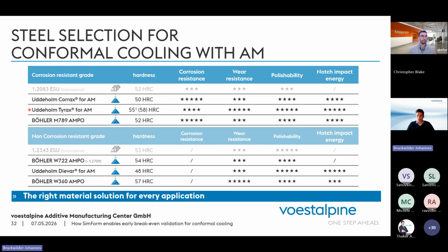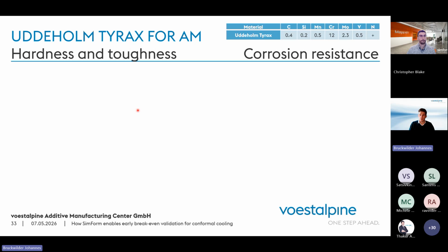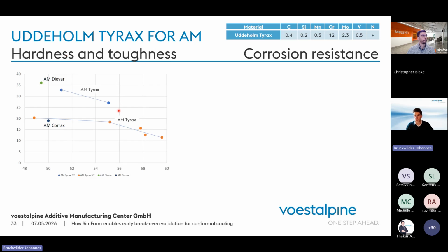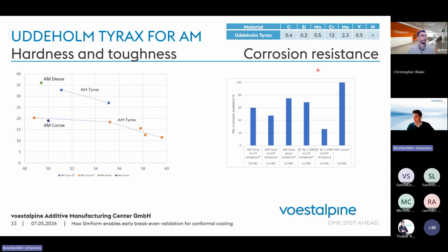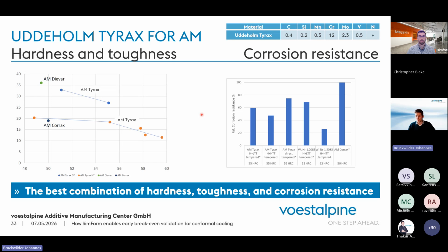In this case, we went for Uddeholm Tyrax. Why? Because that's a great combination regarding hardness and toughness. So here you see with Tyrax, you are at around 28 joule notch impact toughness. And if you have a look at the corrosion resistance, here is Tyrax compared to 2083 with high temperature tempering. So you see that we are even better in a corrosion-resistant way. And you achieve 55 HRC with it. So more or less we have the best combination of hardness, toughness and corrosion resistance. And that's also important regarding the lifetime.